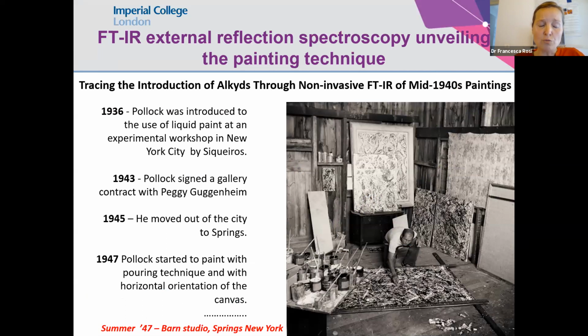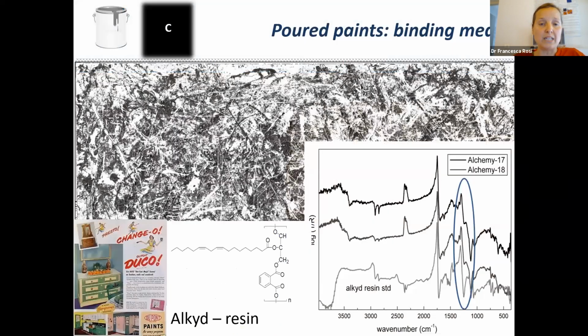FTIR spectroscopy in reflection mode is also very useful for characterization, sometimes for the identification of the organic binder. Identifying the organic binder means unveiling the painting technique of an artist. And I'd like to show you an example of this type of study, reporting some results of this wide study that we carried out on 11 paintings by Jackson Pollock, observed at the Peggy Guggenheim Collection in Venice. The aim of the study was to trace the introduction of alkyd medium through FTIR spectroscopy in a non-invasive way in mid-1940s painting. Jackson Pollock is the father of dripping, and often dripping has been associated with the alkyd medium and the presence of alkyd medium.